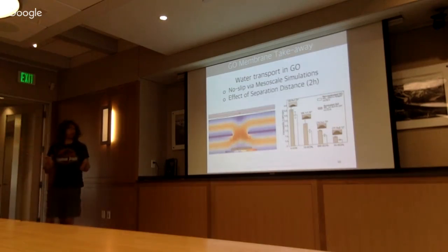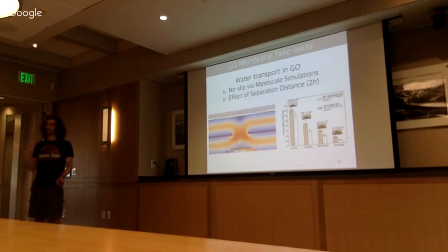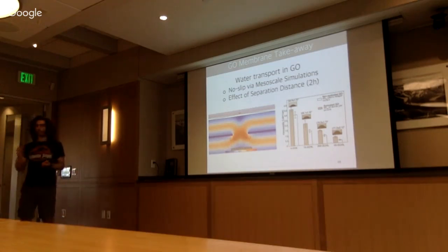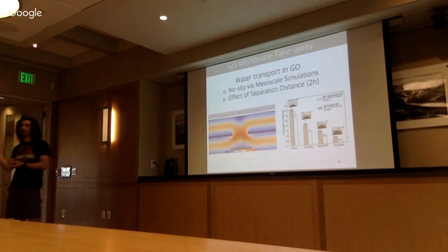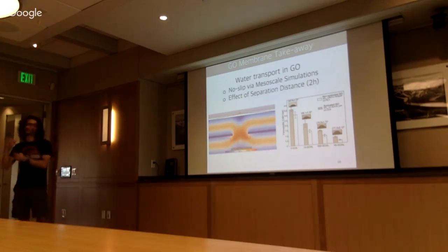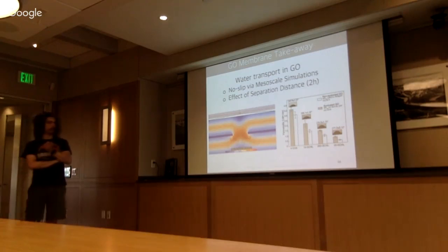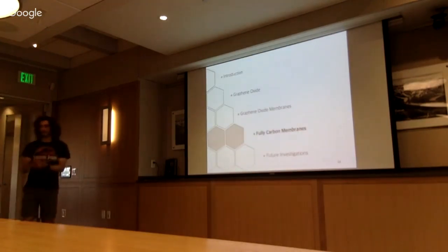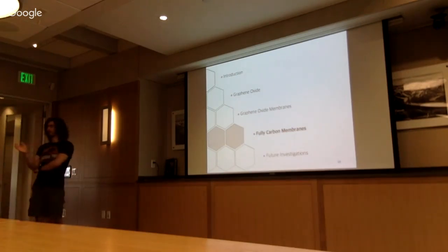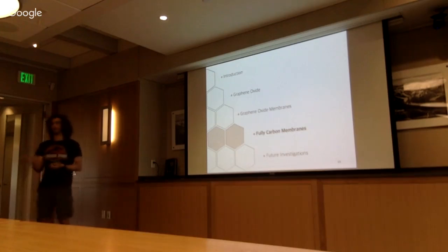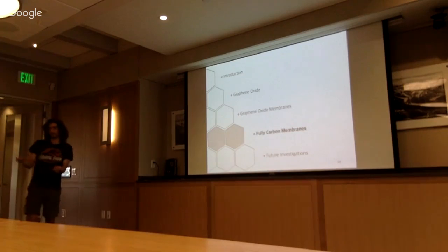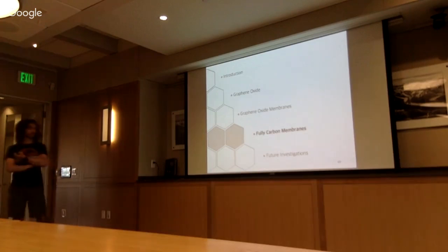Again, just to recap this part, what I showed for the first time, we simulated a graphene oxide system with mesoscale simulations, and also we could really tune its structure at the angstrom level, and we could see the effect of this modification of the structure on the permeability. Then we wanted to go a step further. Most researchers are using graphene oxide to fabricate membranes, but they're still casting graphene oxide onto a polymer. The motivation for using graphene oxide is that it's superior to a polymer. But if you're casting onto a polymer, then you're back to square one. So what we wanted to do is create a fully carbon membrane without the use of polymers.